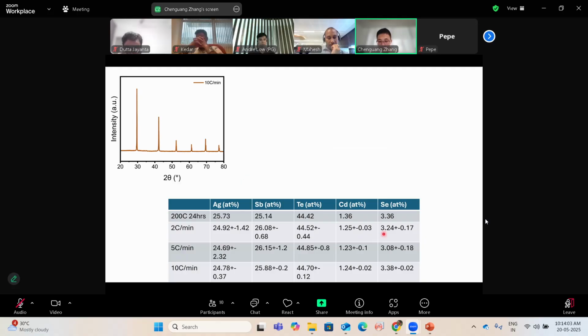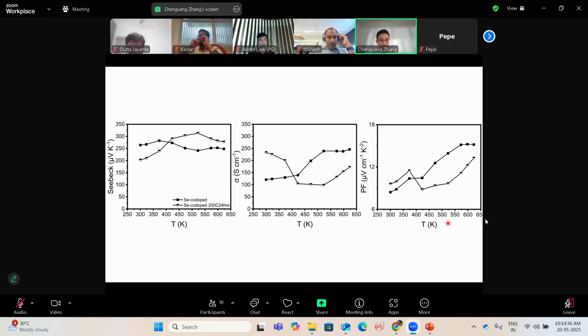And all the elemental distribution is here. You can see that only for the 5 degrees per minute samples, there is a little bit of selenium deficiency here. But for the others, probably because the SEM EDX has a big error bar, I don't think there is too much elemental loss here. And then this is annealing data, post annealing.